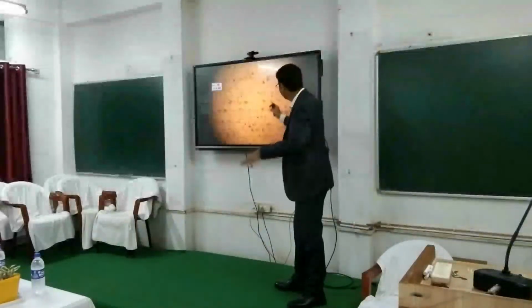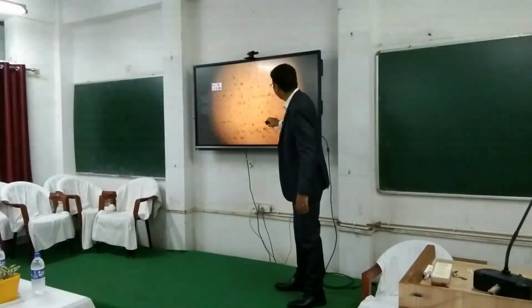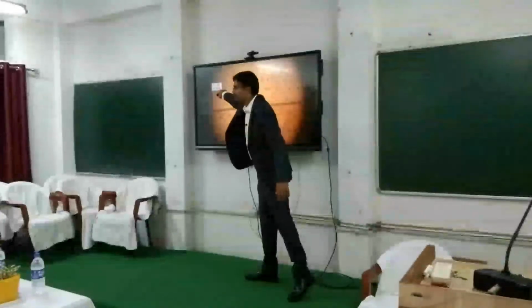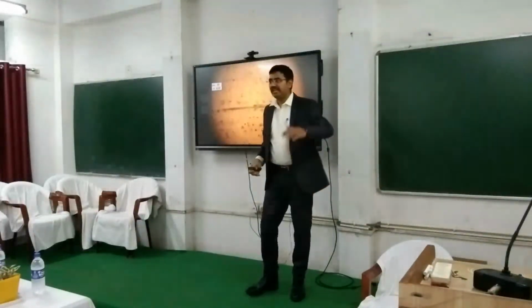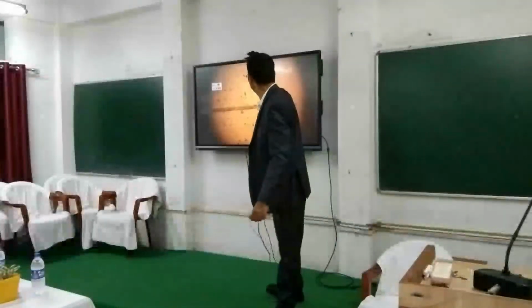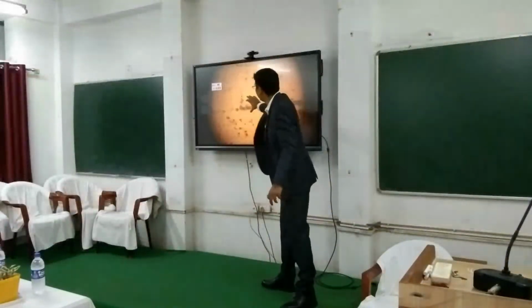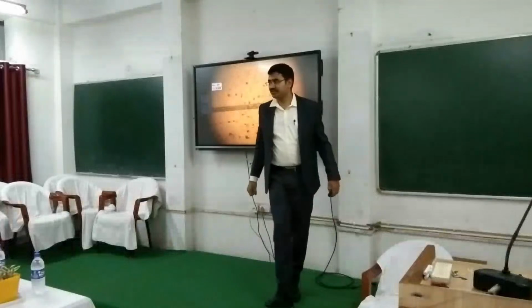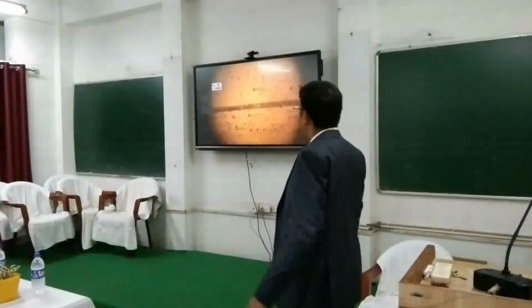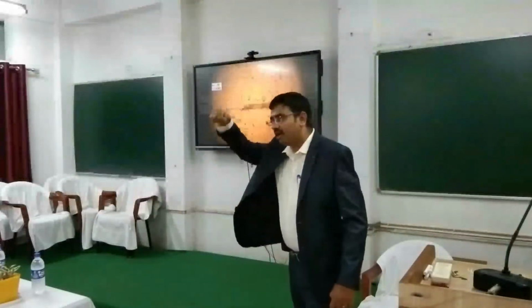The friction is low at 0.3 because initially it has not started, just sliding on top, and as soon as you see the wear starting to occur, the friction actually shoots up to 0.57, 0.6. Initially it is between the ball and the sample, and once you start wearing, transfer film formation occurs, and you see that the transfer film is getting formed on the counterface, and that is actually controlling the coefficient of friction. So by using a transparent ball, here we used a transparent alumina ball, you can monitor in real time what exactly is contributing to the rise in friction.